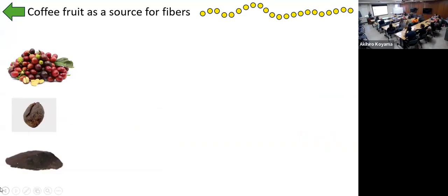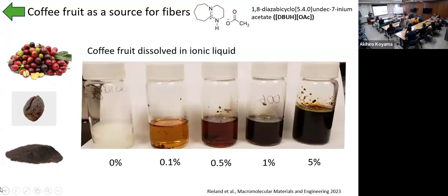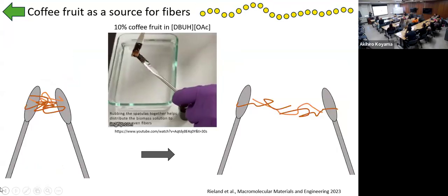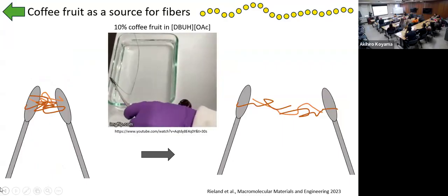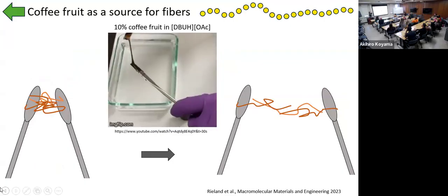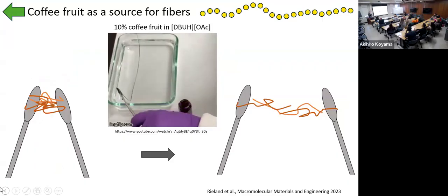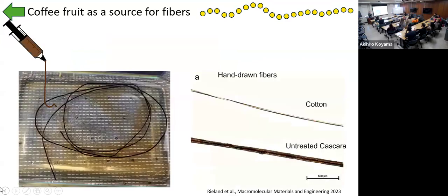So I figured I would start with a place that asks, how much junk can we shove through this? Like if I take dry fruit without any pre-processing, what happens when I dissolve it into these ionic liquids? And what I found was I could get enough rheological properties where I could stretch and kind of extrude fibers from that coffee fruit, but these were so weak once I dried them and got the solvent out that they'd break before I could do any mechanical testing. And so there's a benchmark. We need to do some pre-processing, so we're not going to get away from that. But the next project that I took was, what is the minimum amount of pre-processing that we could do to these materials to actually get functional properties?